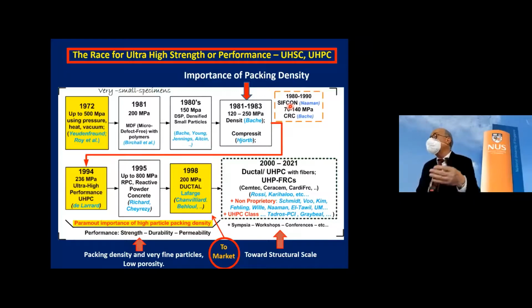That Sifcon has the highest possible fiber content you could put, because you fill it up. There is nothing more you could do. And we were getting, at the time, 70 to 140 megapascal.